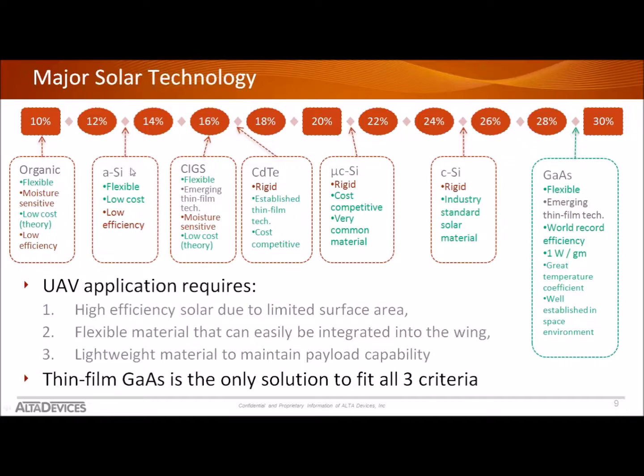The organic material and amorphous silicon, which are really good for indoor lighting, are low efficiency, so 10 to 13% efficient, which is not going to provide much power gain for a UAV. A common thin film material that can be made flexible is CIGS. It is still only 16% efficient, and it is sensitive to moisture. Might not be an issue for UAVs, but CIGS has a potential for low cost. That low cost has not really been realized, with many of the CIGS companies having trouble.